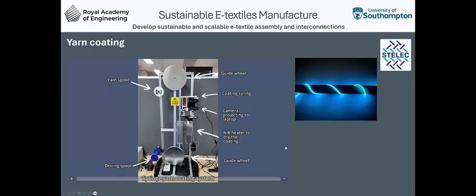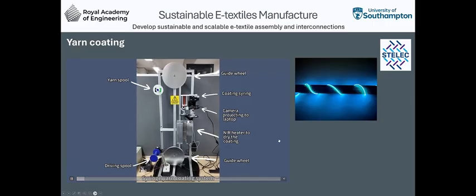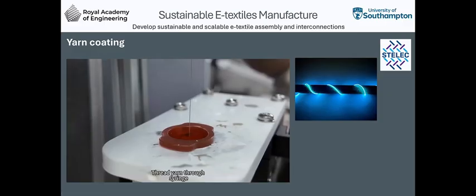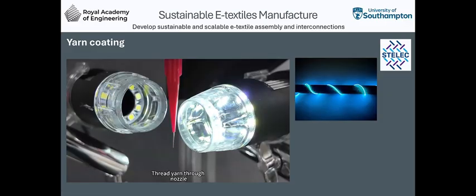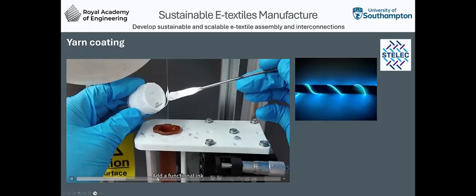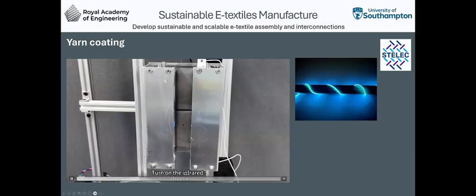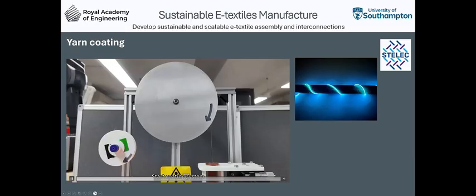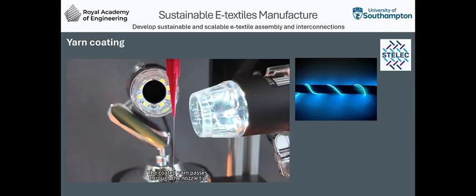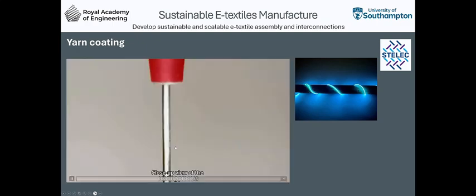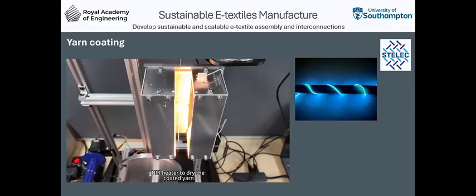Another thing I've just introduced, something we did a couple of years ago, which we're developing quite a lot at the moment, is basically a yarn coating machine where we take the same inks and put the inks in a syringe, and you draw a yarn through the syringe. By controlling the speed of that process and the size of the yarn, it produces a very nicely controlled yarn coating process. This is our very first, very early machine. And you can see the ink coming out of the nozzle. This literally worked on day one. We built the machine, turned it on, and it worked first time.